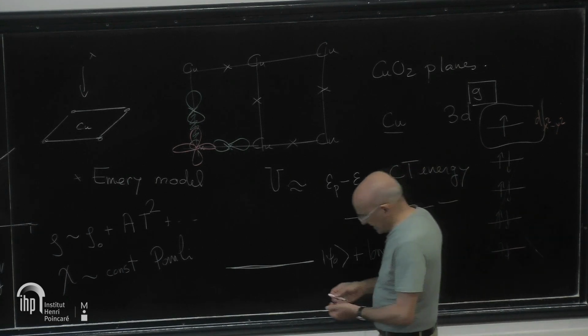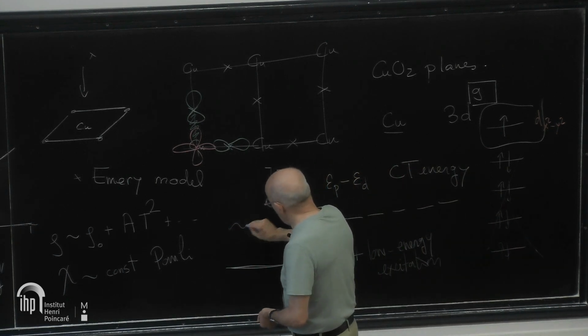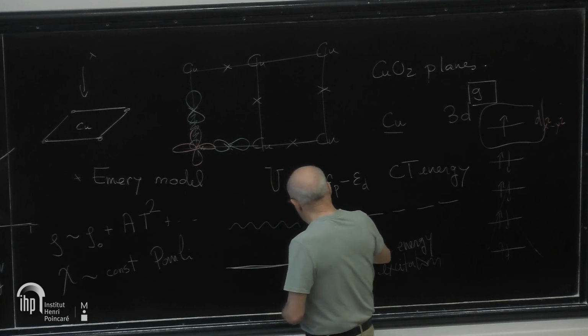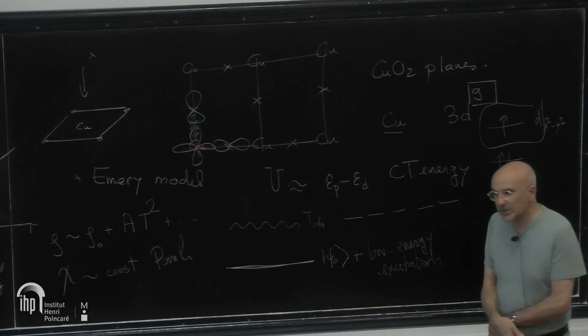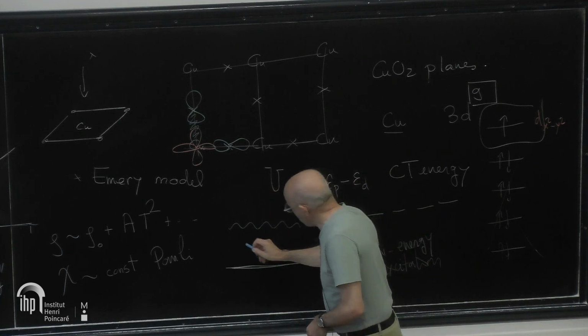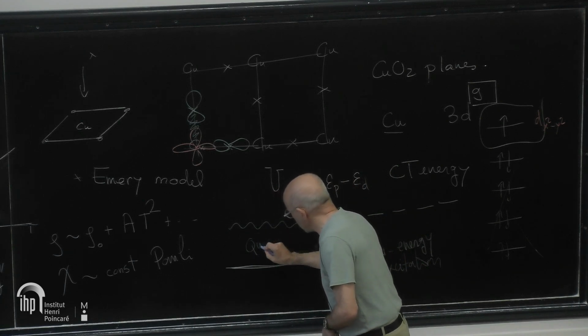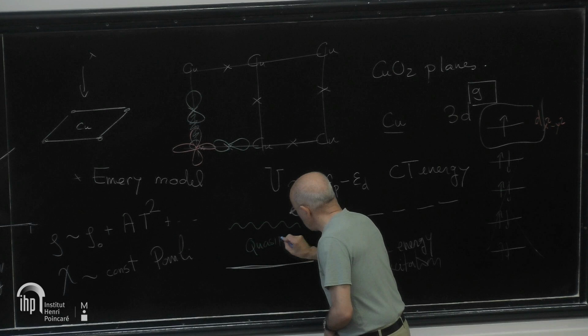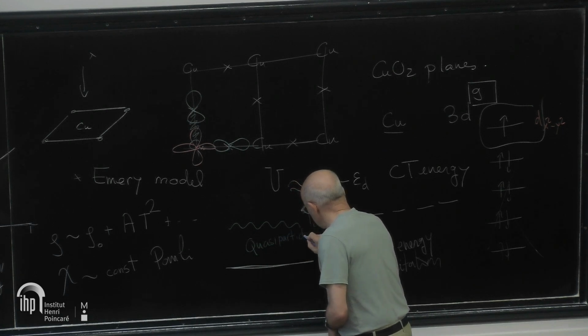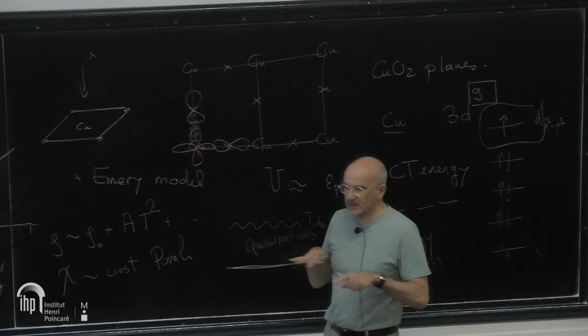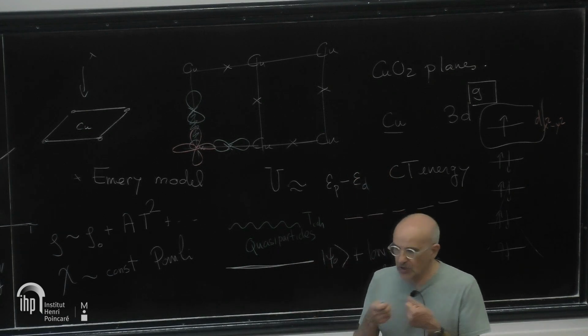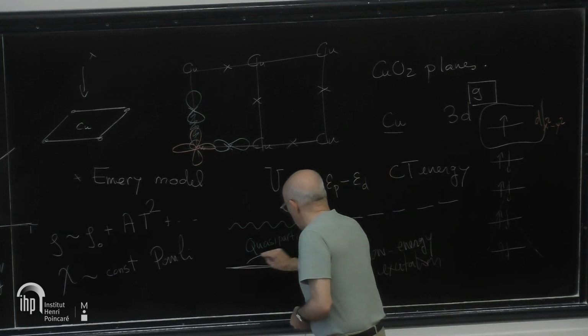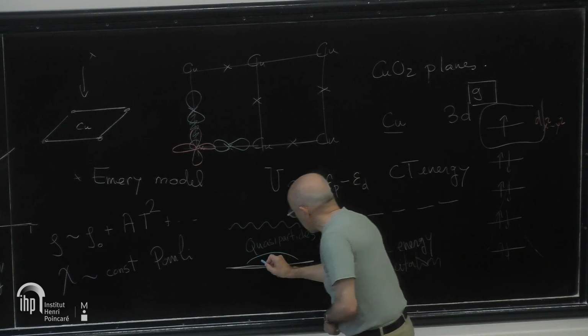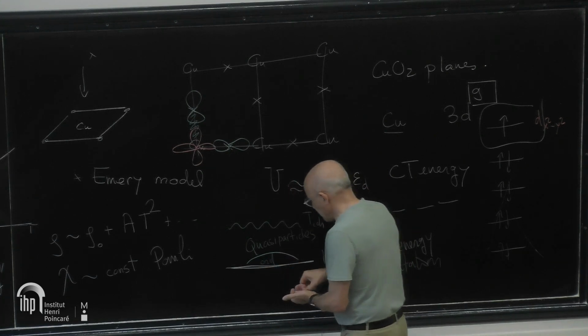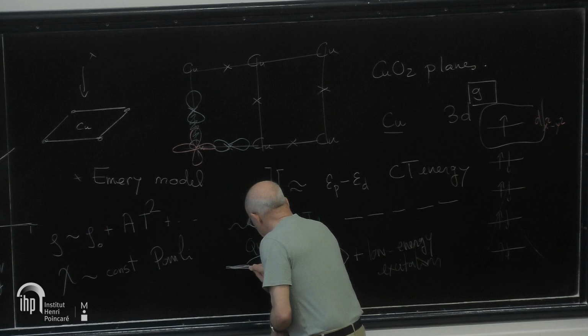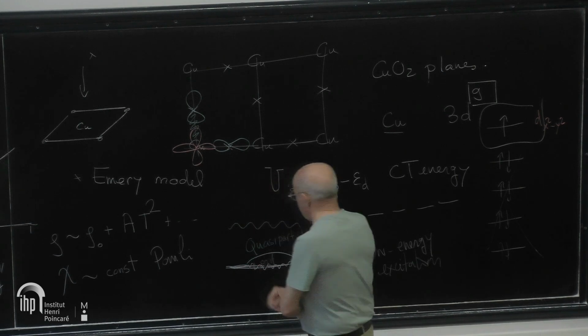And these low energy excitations remain coherent up to a rather high temperature. So here we have well-defined quasi-particles à la Landau. And at some point, this gas of quasi-particles becomes unstable to some instability, and that would be the broken symmetry. So we would have an ordered state here with a quantum critical point between one type of ground state and another type of ground state.